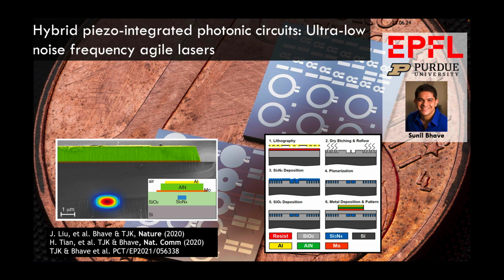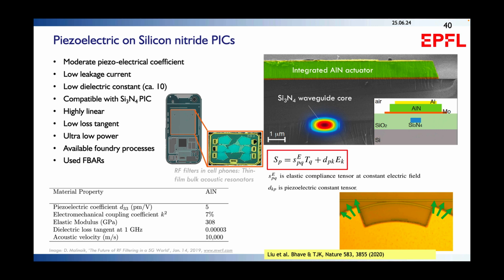The way that the integration works is shown here. We have an optical mode that sits in silicon nitride, and we have the piezo actuator removed from the optical mode, sitting on top here, shown in green. What are we using here? We use the stress optical effect. That is to say, once you apply a voltage to the top and bottom electrodes of the actuator, you generate a stress, and due to the finite Poisson ratio, you create an in-plane shear. And so what happens here is that, due to the elastic compliance and the elasticity-dependent refractive index, we change the optical path length.